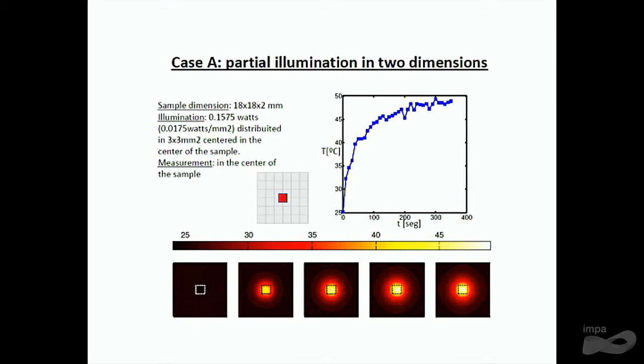So this is the result of the simulation at different times, from 0 to the final time that is around 350 seconds. This is the evolution of temperature in the center of the sample, the exact center. That means it's the center in the 3 dimensions. And this is the evolution of the map of temperatures for zeta equal to 1 millimeter, that is in the middle of the zeta dimension. So as you can see, the temperatures evolve increasingly as time goes by.